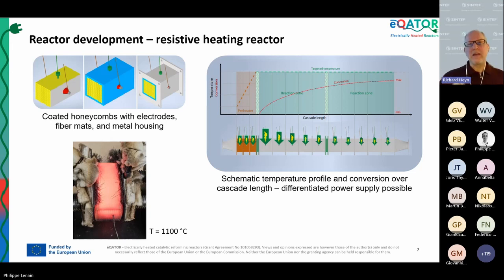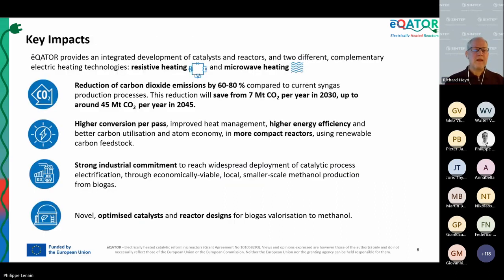honeycombs that can be individually steered for the temperature, so that we can control the power and the heat that goes into each honeycomb in order to match the reaction kinetics that we need to make the most effective synthesis gas. And that is shown on the slide on the figure on the right-hand side, where we have a modeled schematic temperature profile and conversion over this cascade length, where we have multiple honeycombs set up in parallel. At the bottom left-hand side, you see a nice picture of how this works, so that one of these honeycombs can be heated without any issues up to 1100 degrees, and that the temperature is achieved within a minute or so. Next slide, please.